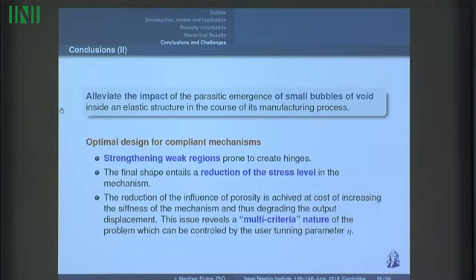For the case of the optimal design of mechanisms, the conclusions are that the weak regions that are prone to create hinges are reinforced, and also there is a reduction of the stress level of the mechanism. So in the experiment I performed, there is a reduction of the influence of this porosity at the cost of degrading the objective function, which reveals some kind of multi-criteria nature of the problem, but can be controlled by tuning this parameter, eta.